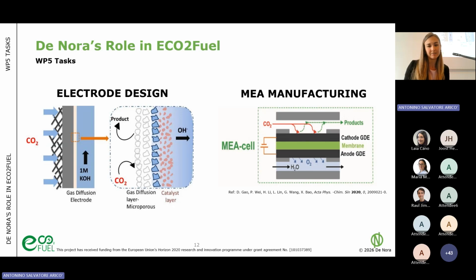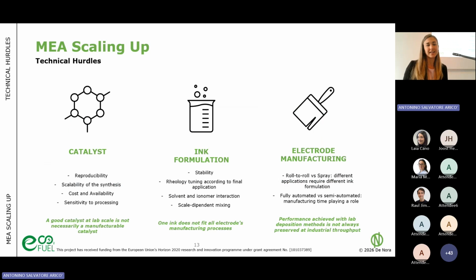It was already described. We know that scaling up has several technical hurdles, starting from the catalyst. This was already discussed by Monolithos, but we have to keep in mind that a good catalyst at lab scale is not necessarily a manufacturable catalyst. We are going to focus in this presentation on the hurdles in the ink formulation and the electrode manufacturing. For example, for the ink formulation, we have to keep in mind that one ink, so one formulation, not necessarily fits all the electrode manufacturing processes. So it really needs to be tailored to the application, working on the stability, on the rheology, on the solvent and ionomer interaction, and also thinking about the scaling up mixing that can be high shear, low shear. So that's something we need to keep in mind.